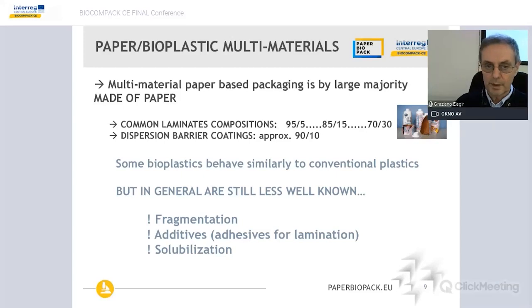When we refer to paper multimaterial, we have to keep in mind that these products are predominantly made of paper. Common laminate compositions can range from 95% paper and 5% plastic, up to 70% paper and 30% plastic for those products that require very high barrier, such as, for example, liquid beverage carton for long shelf life. But also in dispersion barrier coatings, normally the amount of bioplastic is not more than 10%. So we have to do with material that is predominantly made of paper, and it makes sense to recycle these products within the paper stream.